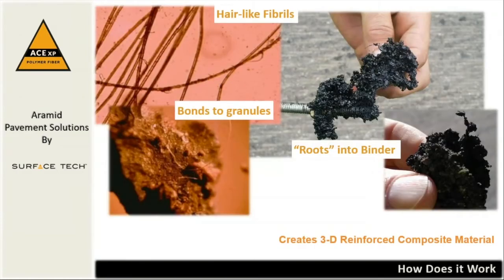So what does Aramid look like and how does it work? If you were to look at an enlarged view of Aramid, you will see that it has a very rough surface texture. This texture allows it to grab onto aggregate surfaces and to root into asphalt binder, creating a flexible mechanical bond and creating a 3-dimensional reinforced composite material when it's mixed with the asphalt.